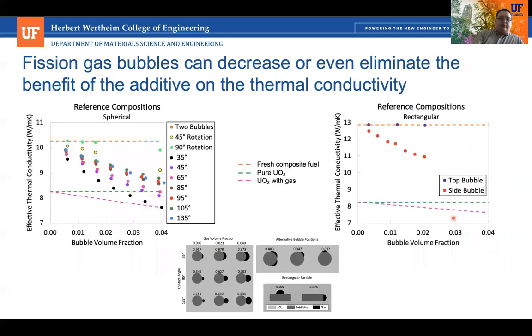So here are the results. Specifically, this is for beryllium oxide and uranium dioxide at 300 Kelvin. And here I'm showing some lines for reference. We have a fresh composite fuel without fission gas, which is this orange line. We've got the green dashed line here, which is pure UO2, and then the pink line is UO2 without additive, but with a gas bubble of the same volume fraction.